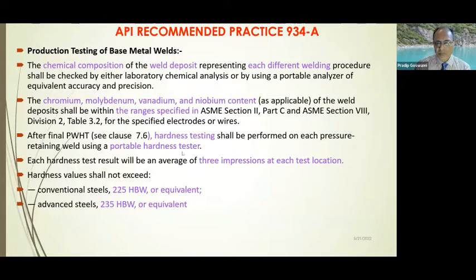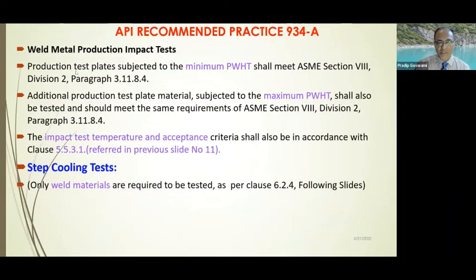After final post-weld heat treatment, hardness testing is a must, and each hardness test will have an average of 3 impressions. And as I said before, the hardness shall not exceed 225 Brinell or 235 Brinell for the advanced as well as the conventional steels. Weld metal production impact test is again a must. And during this impact test, one needs to find out the values, and basically step cooling test, as I mentioned here, only weld metals are required to be tested as far as the production coupons are concerned.